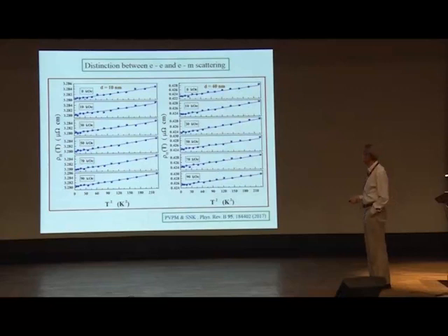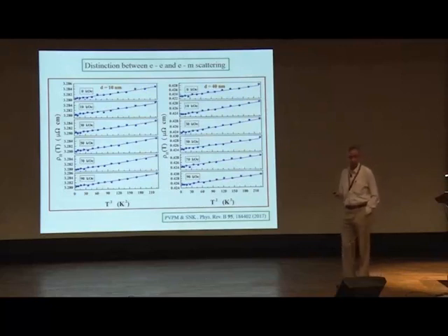So it's a clear indication that up to about 10 Kelvin or so, it is just the electron-electron scattering that is dominant. In fact, in literature, for more than 6 decades, most of the people believed that this T-square dependence comes from electron-magnon scattering, not from electron-electron scattering. But a simple experiment, I don't know why they didn't think of a simple experiment to distinguish between these two.